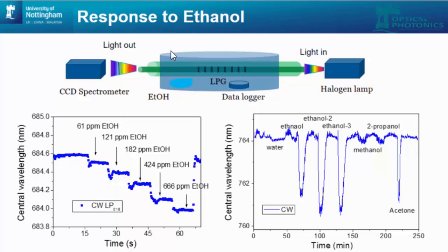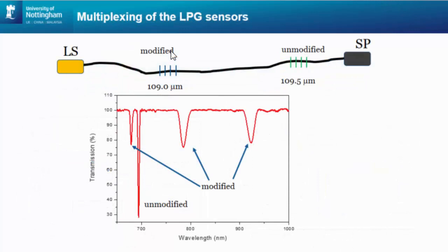Penetration of the gas into the pore will change the refractive index of the film, and we're measuring this refractive index. As I mentioned earlier, it's not sensitive to humidity, but there is a temperature sensitivity of these long period gratings via the thermo-optic effect, and also if there is high strain, you'll have an elongation of the optical fiber, so it will change the grating period. So the position of these bands will change.